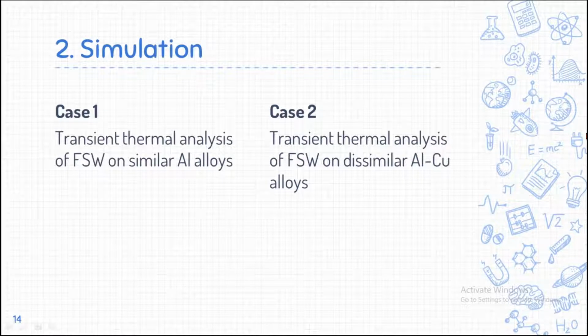So in this simulation, we will see two cases: transient thermal analysis of friction stir welding on similar aluminum alloys, and transient thermal analysis of friction stir welding on dissimilar copper to aluminum alloy welding cases. Before going to the simulation, a main point to be remembered in friction stir welding, which many scientific journals have also reported, is that to get a good weld one should obtain around 75 to 85 percent of the melting point of that particular alloy. For example, the aluminum melting point is 660 degrees centigrade. To get a good weld in the friction stir welding process, one should have a temperature or heat input around 75 percent of that particular melting point.